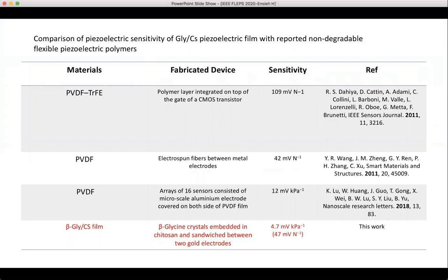And this table shows a comparison of piezoelectric sensitivity of the glycine-chitosan piezoelectric device with reported non-degradable flexible piezoelectric polymers such as PVDF and PVDF-TrFE. Actually, the sensitivity is still lower, but it is comparable with this kind of non-degradable flexible piezoelectric polymers.